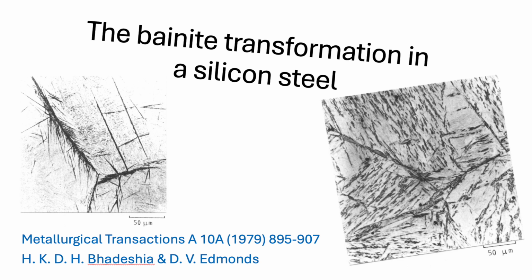It's classic evidence for precipitation from a supersaturated solid solution. If the carbides were forming at the moving interface during growth, you'd expect them to have a single, unique orientation relationship with the austenite they grew from. But forming later, inside an already formed, supersaturated ferrite crystal, allows them to nucleate on multiple crystallographically equivalent variants of the precipitation habit plane. Ah, I see. The location and the multivariant nature point away from interface formation and towards precipitation from within. Unmistakably. It's strong evidence that the ferrite formed first by shear trapping carbon, and then the carbon precipitated out as cementite internally.